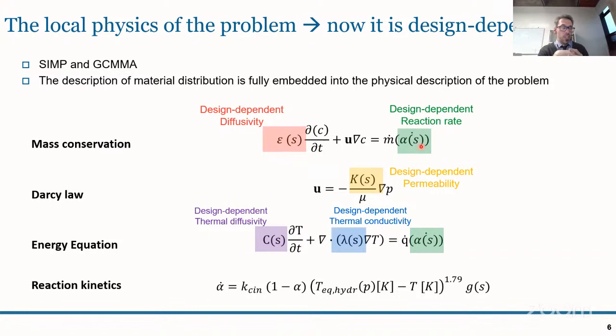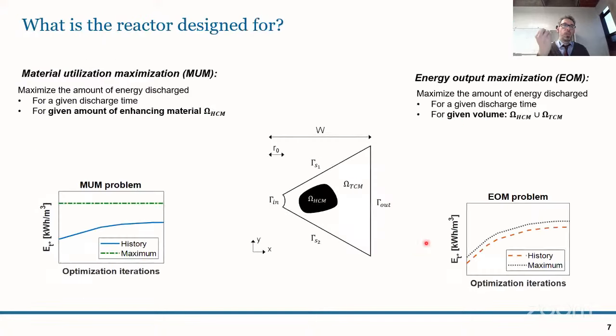What is highlighted here with these boxes are the thermophysical properties and parameters that become design dependent when included in a topological optimization framework. So the diffusivity, the porosity of the material, as well as the thermal diffusivity, as well as the reaction rate, because obviously where there is thermochemical storage material, we have a reaction rate potentially different from zero, and where instead we have a heat exchanger material, obviously there is no reactivity taking place. For performance indicators, as I mentioned, what we typically pursue are two paths.